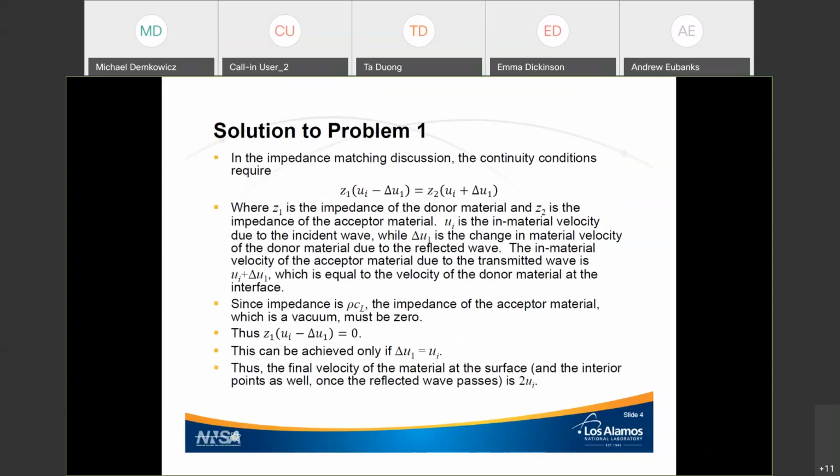No, there's not a discontinuity. The atoms at the surface are partially responsible for the potential well that the atoms deeper in sit. When those atoms move, they apply a force to the atoms that are next to them, causing them to move as well. And that is the fundamental origin of the wave that goes back. If you remember in the discussion that we had of how a wave is generated, I said, apply a time varying force at the surface. I didn't say what caused that force. Just apply a time varying force.